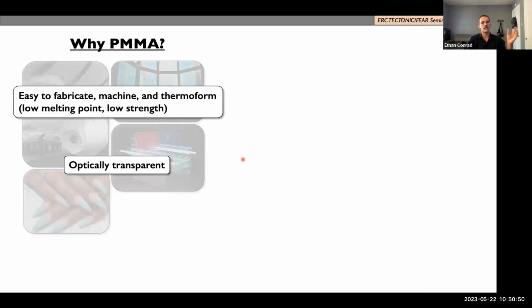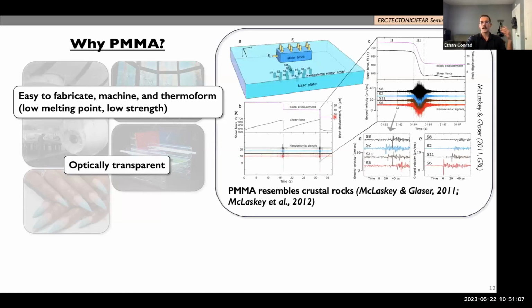And that's because it's really easy to fabricate, machine, and thermoform. This is because it has a low melting point and low strength, and that's ideal for our experiments as well. We can easily melt the plexiglass, and it's optically transparent, meaning that we can view the evolution of the interface as the event is evolving. And PMMA has been used extensively in friction experiments.